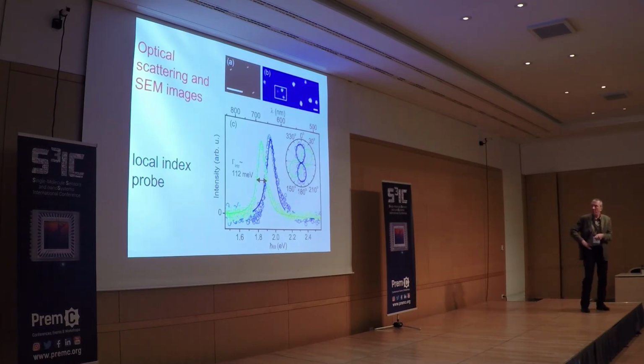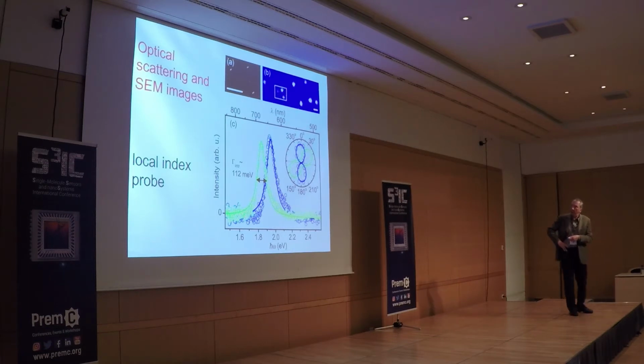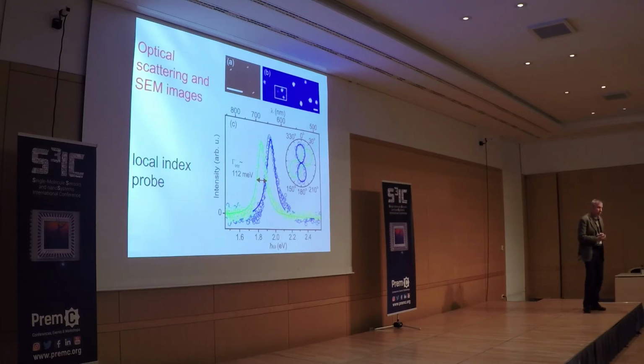So you see here a few examples of nanorods that we imaged either optically here or within the SEM by electron microscopy. And you can go on each of these particles. We can make sure in this way that this is a single particle because we have the image. And we can look at the resonance, and you see it's a nice Lorentzian shape with a given width. And of course, because this particle is slightly different, the position of the resonance is slightly shifted according to the aspect ratio of the particle.